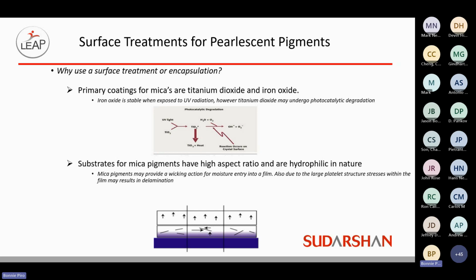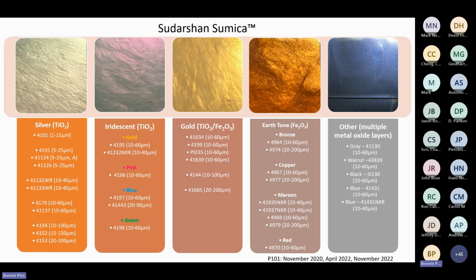In water-based type formulations, because these pigments have such a high aspect ratio and are hydrophilic, they may not be able to wick properly. And so when the moisture comes out of the film, or goes into the film, there might be some wicking action caused by the mica and the water associated, which can lead to a deterioration of gloss. Of course, there are many color and size options with the Sudarshan portfolio of mica pigments. So there's many here to offer for your formulation needs.